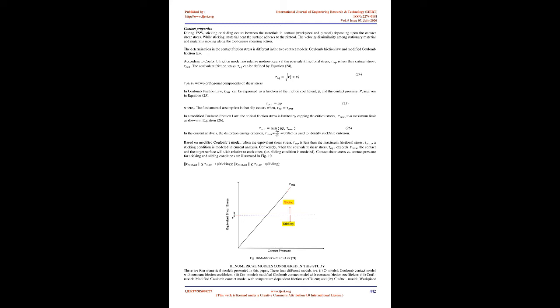Here, T represents the absolute temperature of the workpiece, T∞ the ambient temperature, and h the convection coefficient. During the experiment, see Fig 2, the presence of the chill bar helps to clamp the workpiece. A high heat transfer coefficient of 100 W/m² has been assigned on the top surface of the workpiece caused by chill bar 24. Heat loss from the side surface of the plate is calculated using a heat transfer coefficient equal to 30 W/m², assigned for convection from aluminum to air 42.